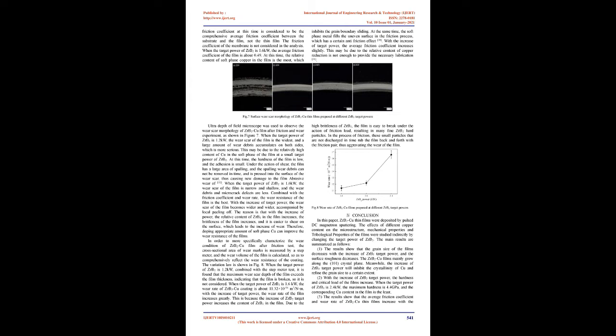According to Griffith microcrack theory, fine Cu grains are dispersed between ZrB2 columnar crystals, which shortens the crack length between columnar crystals and improves the quality of the film. The fracture strength and hardness of the film were studied [28], so the hardness of the film reached the maximum